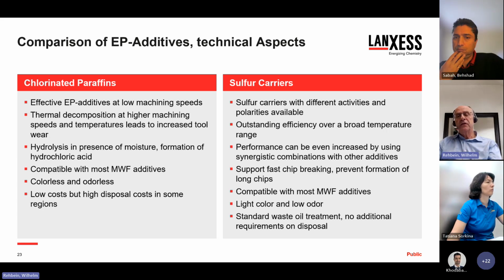Sulfur carriers, on the other hand, are available with different sulfur content, different activities, different polarities or molecular structures, so they can be easily adapted to the specific requirements of a single metalworking process. And they show outstanding efficiency over a broad temperature range from slow to high-speed machining processes. Their performance can even be increased by synergistic combinations with additives like over-based sulfonates, polycarboxylates, or some anti-wear additives.